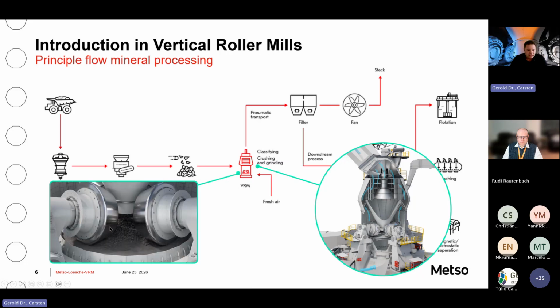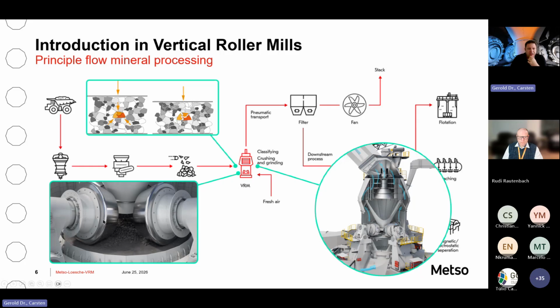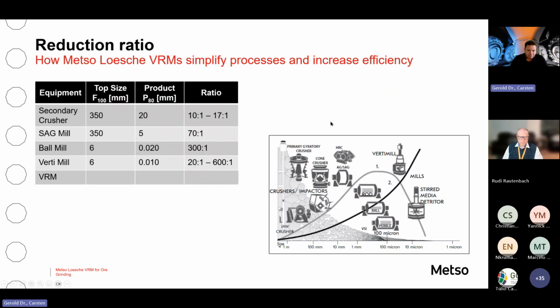We will talk a little about the way the mills are built up. The comminution zone has the grinding table and the grinding rollers, in our case conical. The grinding, or crushing and grinding, happens in a compressive bed, and through the conical rollers we combine compressive and shear forces, which gives us a pretty good degree of liberation. And like I said, having a dry grind product, we can buffer between comminution and the beneficiation processes.